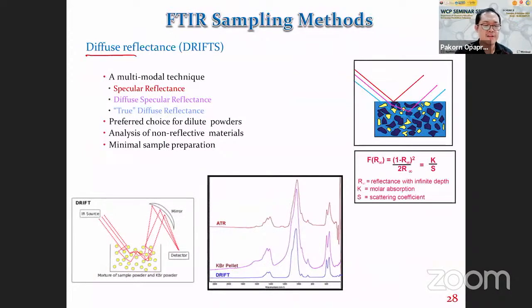Another mode is diffuse reflectance, or DRIFT mode. This mode is usually suitable for samples with dark color that can absorb so much of the infrared light. So we can mix the sample with KBr to dilute the concentration, and then we just shine light onto the sample and measure the diffuse reflectance signal.